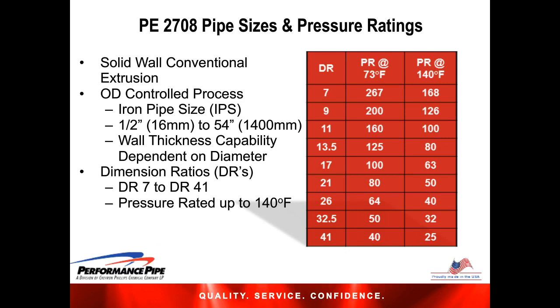Like standard PE 4710 materials, the PE 2708 is a solid wall pipe produced by conventional extrusion. The process is OD and wall thickness controlled to produce sizes from half-inch to 54-inch outside diameter with dimension ratios, or DRs, ranging from DR7 to DR41. In addition to the pipe's hydrostatic design stress we discussed, the pipe's specified dimension ratio, or DR, is used to determine the pipe's pressure rating or design pressure. Very simply, this is the outside diameter, OD, divided by the pipe's minimum wall thickness. So for a given outside diameter, the lower the DR, the greater the wall thickness.